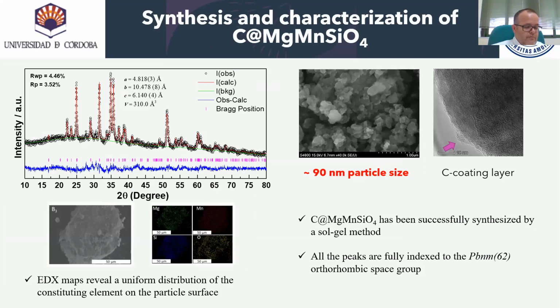A carbon-coated magnesium manganese silicate has been successfully synthesized by a sol-gel method. The crystallinity and phase structure are determined by X-ray diffraction. The Rietveld refinement confirmed the adequate indexation of the space group Pbnm of the orthorhombic system. Calculated parameters are also presented here.